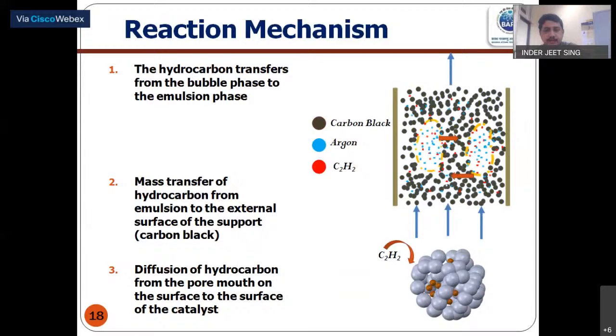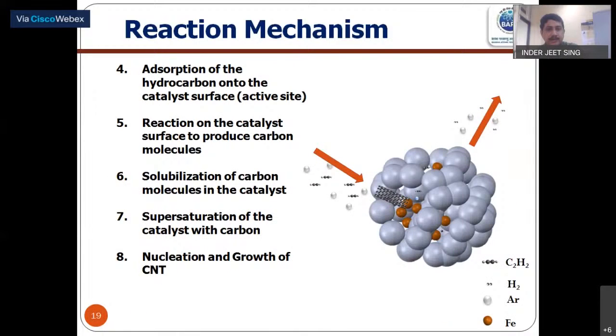And then what we can show after coming, it is adsorbing. The fourth step is the adsorbing onto the surface of the catalyst. After adsorption, the reaction on the catalyst surface happens to produce carbon, meaning acetylene is breaking into carbon atoms and hydrogen, and this carbon has solubility in the iron catalyst. So it is getting soluble, then saturated, then supersaturated, and once supersaturation occurs, the carbon nanotube comes out, like this. That is the step of nucleation and growth, and the hydrogen and the argon come out.